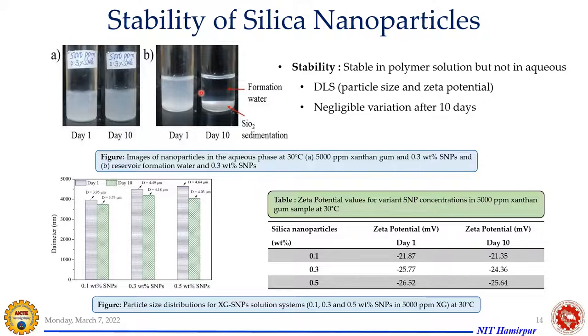We took formation water that we prepared synthetically in our lab, and this is the nanoparticle. We mix it and keep it in suspension. There are various techniques like the ultrasonication technique. This gives the nanoparticles in suspension. Then you see after a duration of 10 days, all of the nanoparticles get aggregated and settle at the bottom. So the sedimentation behavior is quite high.